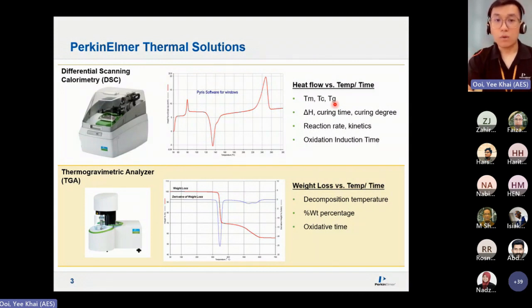If you want to do identifications, this is especially dangerous if you have a standalone DSC and you run it blindly, because if you run until it decomposes within your furnace chamber, then of course contamination is going to happen, and you're also going to damage the furnace itself. So before subjecting to a DSC scan, you should always run TGA first to determine what is the safety temperature, or what we call the decomposition temperature.